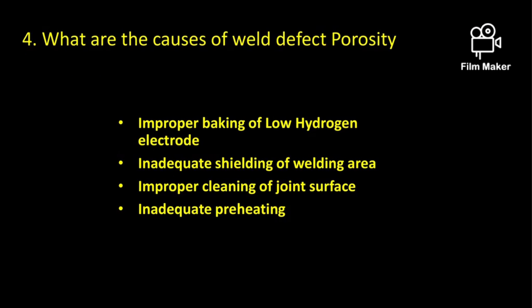What are the causes of the weld defect porosity? Improper baking of low hydrogen electrode, inadequate shielding of welding area, improper cleaning of joint surface, and inadequate preheating.